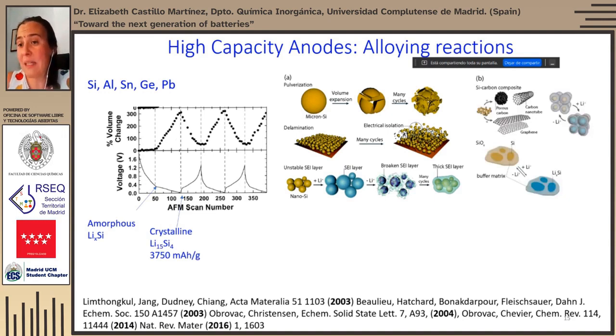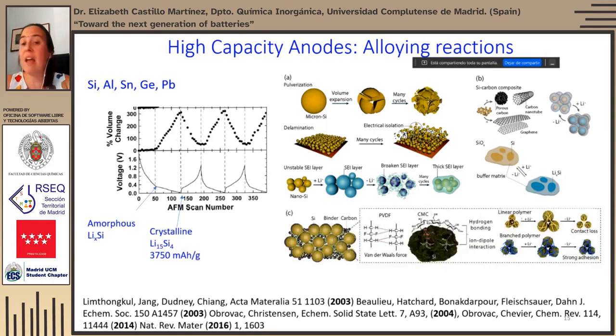Many strategies have been developed to try to overcome this, like compositing nanoparticles instead of micron size with carbon materials, putting silicon nanoparticles in a silicon oxide matrix that can buffer the volume expansion, as well as using different types of binders, which could be electronically conducting, and branched polymers, which can have a better adhesion to the silicon particle.